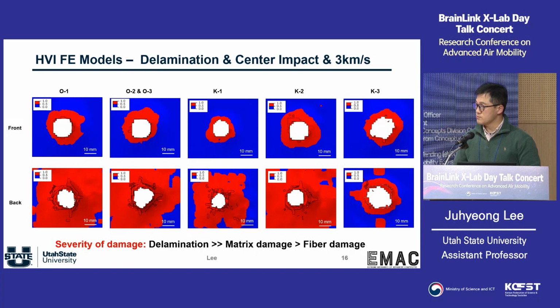Delamination is simply when you have a sandwich panel and then you separate it in the applied direction. And delaminations are very unclear because you can't easily evaluate the delamination. So this model gives you how much delamination can be driven from the impact. The red area indicates fully delaminated, and the blue area means undamaged and safe. So depending on the choice of the pattern, you can see less or more delamination after the impact. If you think about the severity of the damage, of course, delamination is really bad, followed by the matrix and the fiber damage.